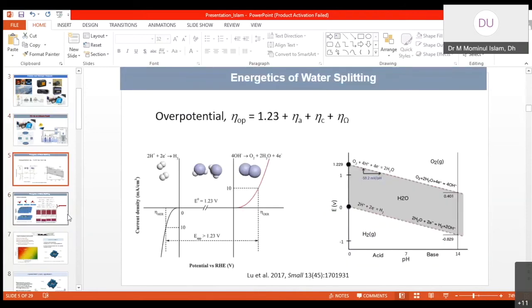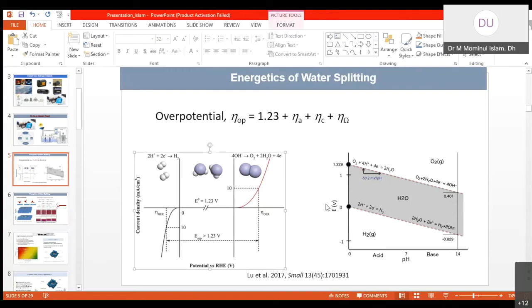Dr. Mo, I was talking about this point that water splitting needs some overpotential, and this overpotential comes from the thermodynamic potential, the anodic and cathodic overpotentials, and the ohmic overpotential. The most important point is that if we change the medium from acidic to basic, the hydrogen evolution overpotential changes, and the oxygen evolution overpotential also changes. If we keep this reaction in a highly acidic medium, then we can evolve hydrogen without applying any potential. So only the kinetic hurdle and other energy needed for the oxygen evolution reaction remain.